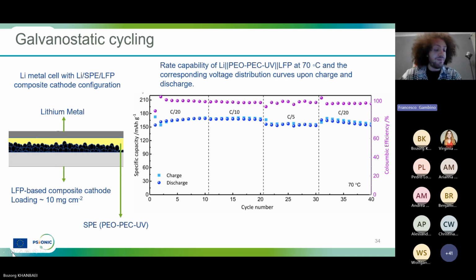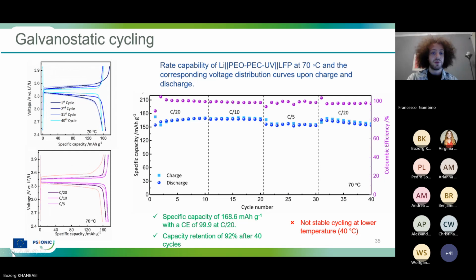So after, we tested this polymer electrolyte in an LFP-based cell, and we used a composite cathode with high loading, around 10 milligram per square centimeter. Next slide, please. Okay, from the rate capability test, we observed that at C over 20, there is a high specific capacity at around 168 milliampere hours per gram, and also a very high Coulombic efficiency of around 99.9%. Also at C over 10, there is a great retention of the capacity that is around 160 milliampere hours per gram. But when we tested this membrane at 40 degrees, we didn't achieve the results that we expected to have. So, next slide.